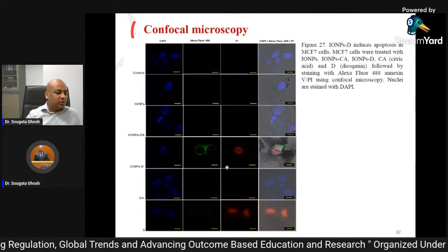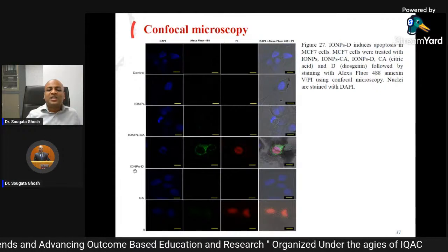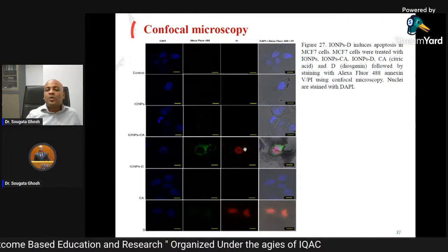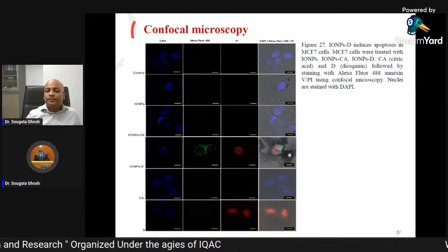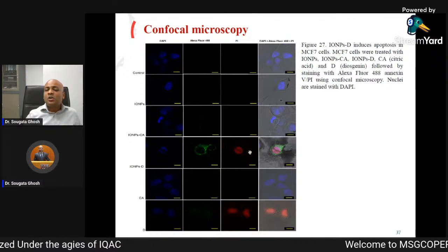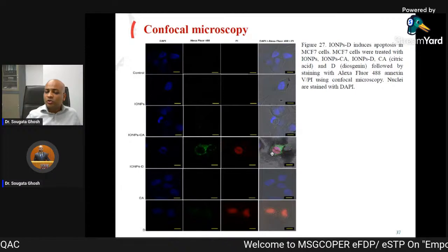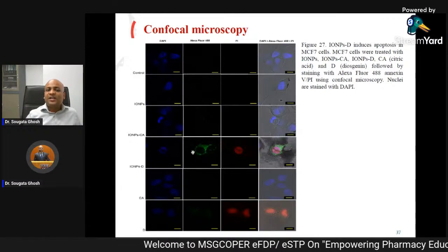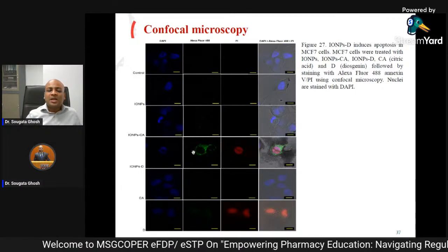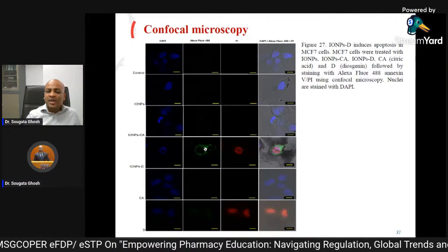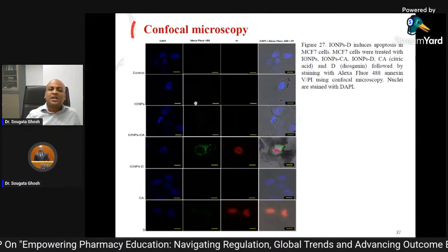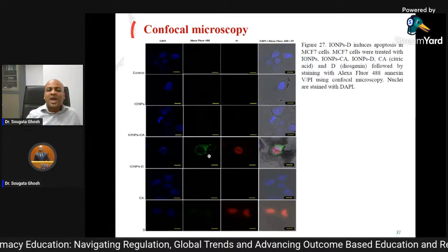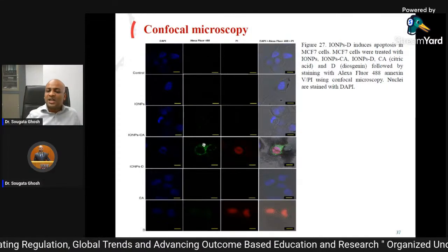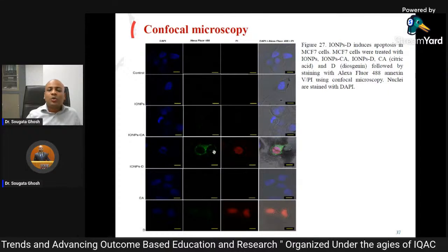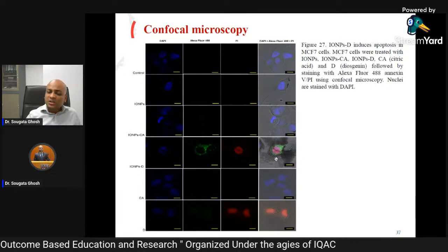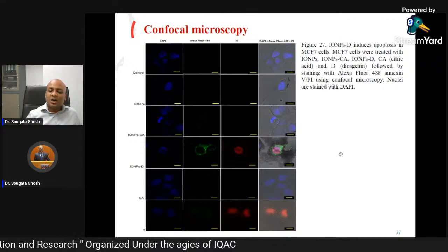Now we tried to see whether it is apoptosis or necrosis, and you can see in iron oxide diosgenin, we can see maximum, both the green and the red. The propidium iodide staining was also here, and Alexa Fluor 488. It is similar to the previous dye, like Annexin V Alexa Fluor or FITC. It is similar. Alexa Fluor is similar to Annexin V FITC. So it also stains the phosphatidylserine. So you can see dual staining positive over here. So this confirmed that it was undergoing apoptosis.